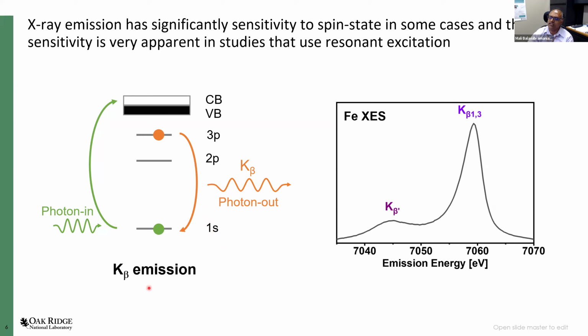One of the processes that takes place is called the K-beta emission, where the electron falls from a 3p level to fill the 1s core hole state, giving rise to the K-beta fluorescence. If this fluorescence can be analyzed with about 1 eV resolution, you can get a spectrum which looks somewhat like this, where you have what is called the K-beta 1,3 main line and the K-beta prime satellite line. It turns out that due to the exchange interaction between the 3p hole state that is created during the X-ray emission process, along with the spins that are present in the 3d manifold, the 3p-3d exchange interaction gives rise to the splitting, and it encodes the spin information regarding what is there in the d manifold as viewed very locally on the atom that is being photo-excited.